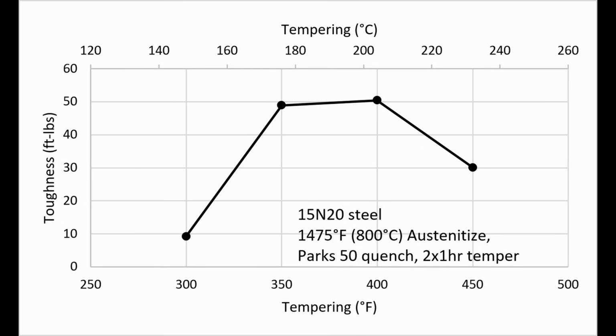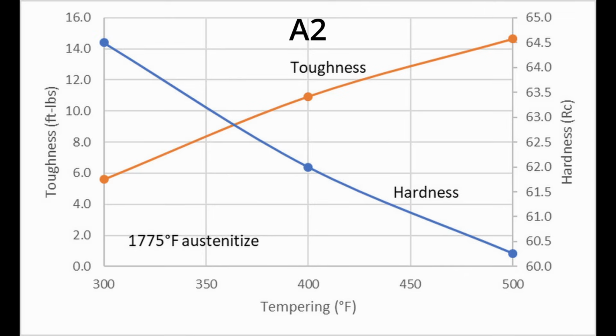Now, there was higher hardness with the 300 degree, but you're kind of giving up that amazing toughness you can get with 15N20 by only tempering at 300 degrees. Other steels have lower toughness to begin with, and so their increase in toughness is often more linear. So 300 degrees can make more sense.